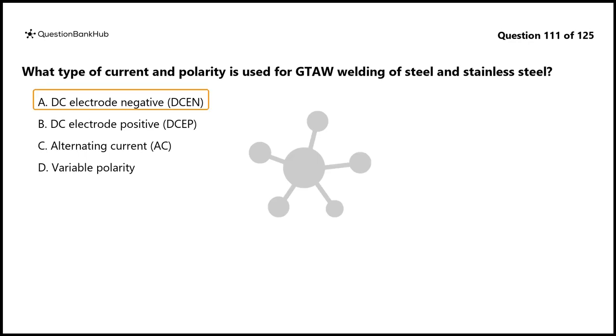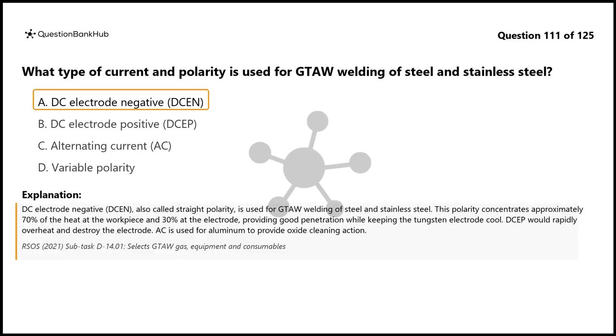The correct answer is A. DC electrode negative, DCEN. DC electrode negative, DCEN, also called straight polarity, is used for GTAW welding of steel and stainless steel. This polarity concentrates approximately 70% of the heat at the workpiece and 30% at the electrode, providing good penetration while keeping the tungsten electrode cool. DCEP would rapidly overheat and destroy the electrode. AC is used for aluminum to provide oxide cleaning action.